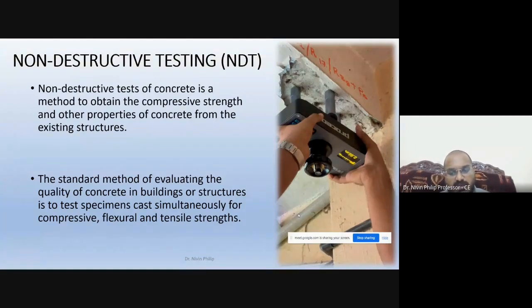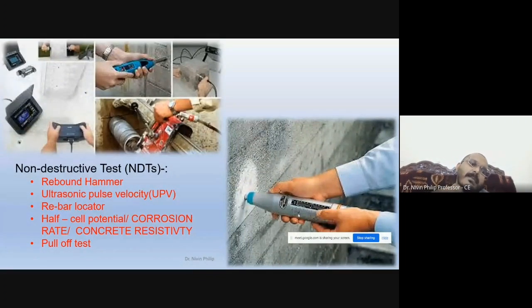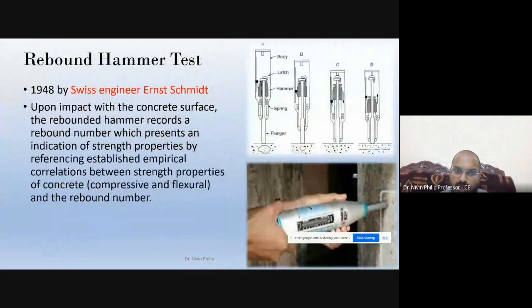In non-destructive testing, we are measuring different kinds of properties like compressive, flexure, and tensile. These are some of the techniques we are using for non-destructive testing, like the rebound hammer, which most of the engineers already know. We are measuring the compressive strength. Then UPV, then the rebar locator to identify the exact location of the rebar, whether it is as per the specification given in the structural drawing, or when we are taking any corrosion test, we have to locate the reinforcement. Then half cell potential to identify the corrosion rate. You have to identify how much corrosion happened to the steel. Then pull-off test to identify the cover. Let's go deeper into that.